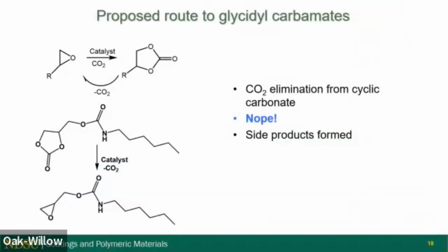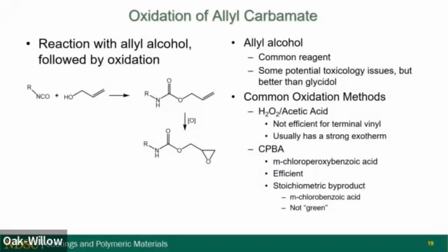We had initially proposed that we could take an epoxy and make it cyclic carbonate, react that onto our system, and then reverse this reaction to the epoxy. And as in a lot of research, we found this didn't work at all. And again, you find all kinds of literature where people are doing this reverse reaction, but in this system, it didn't work at all. We got a lot of byproducts. So actually, the side products that we formed were of interest, and we're actually filing patents on the side products as a different route to these cyclic materials. But anyway, it was like, what do we do, you know?